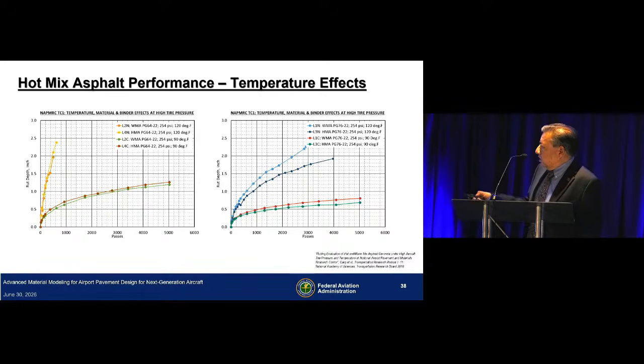As you can see on the left side, we have 2 lines for each material. One is warm mix asphalt, the other is hot mix asphalt, and this is for PG 64-22, so unmodified binder, but tested at 120 degrees and 90 degrees. These temperatures are 2 inches below the pavement surface, so when I say 120 degree pavement temperature, you're looking at surface temperatures of around 160 to 170 degrees Fahrenheit. And you can clearly see the difference in the performance. Here the failure criterion was 1 inch of surface rut. You have pavement sections failing in less than 200 passes, whereas at 90 degrees, you're close to 3,000 passes. So that's a pretty significant effect of temperature.